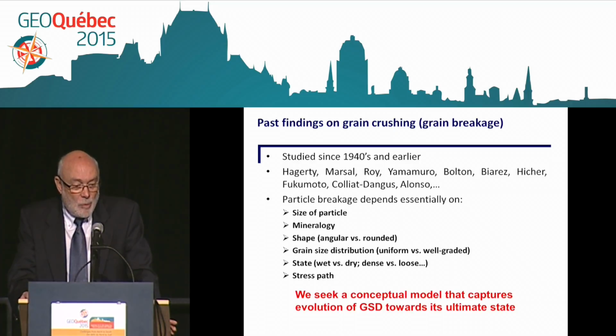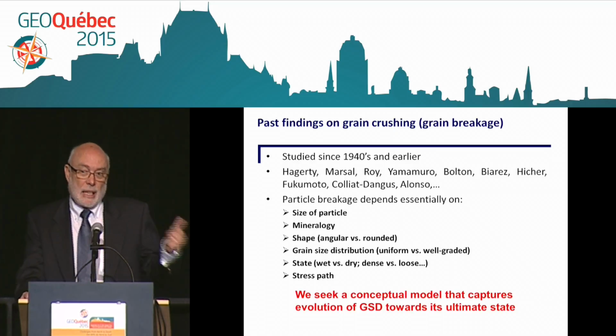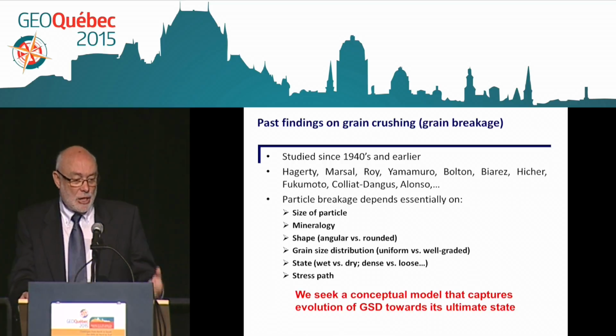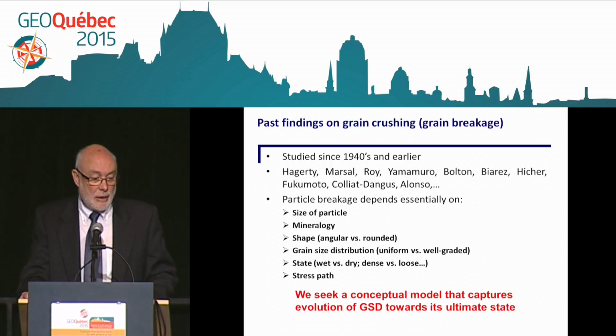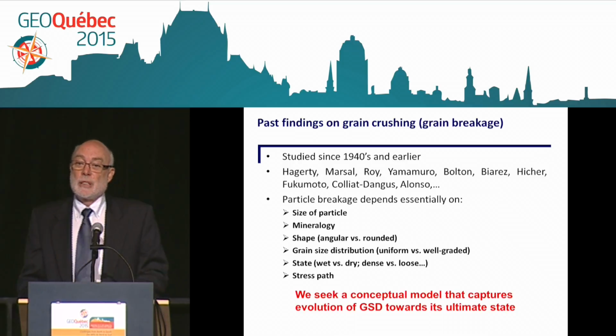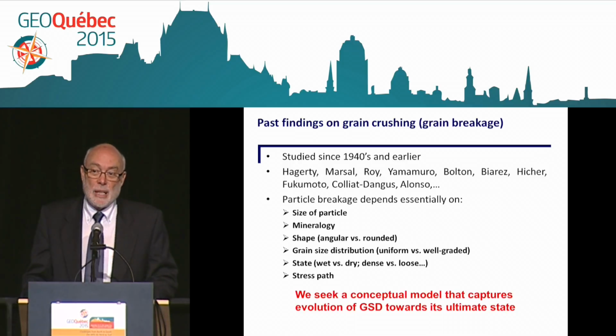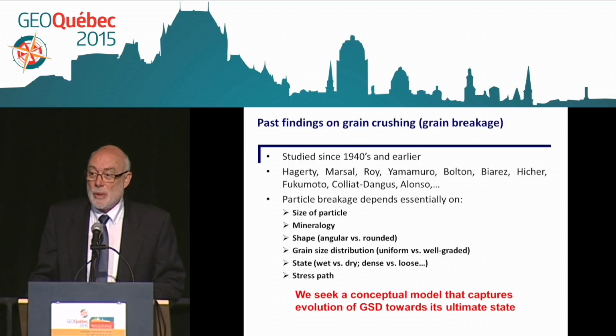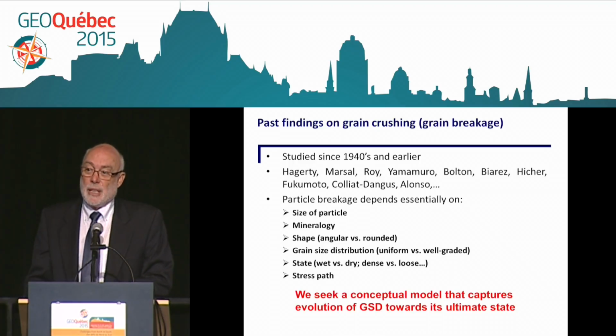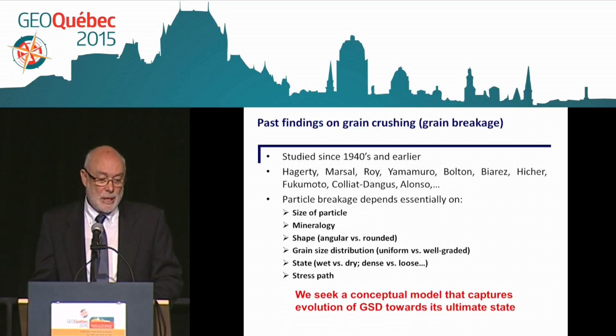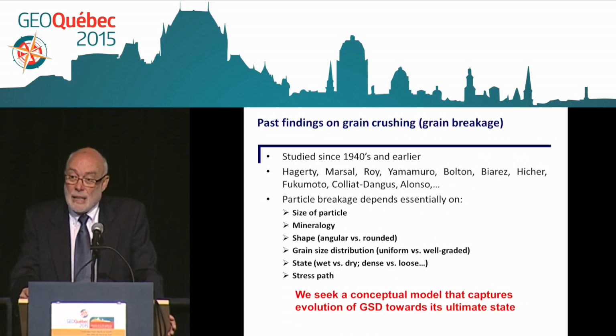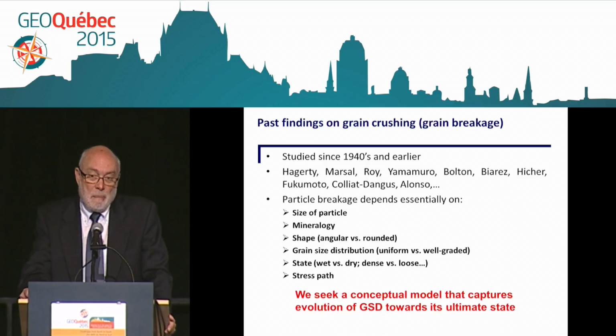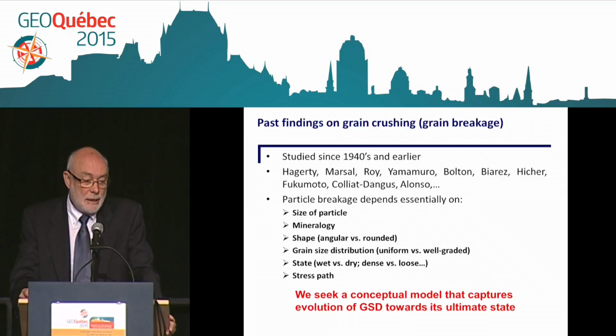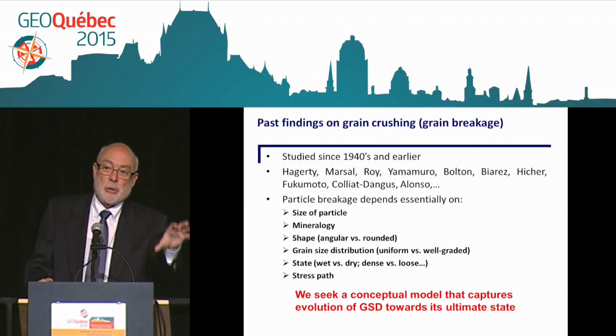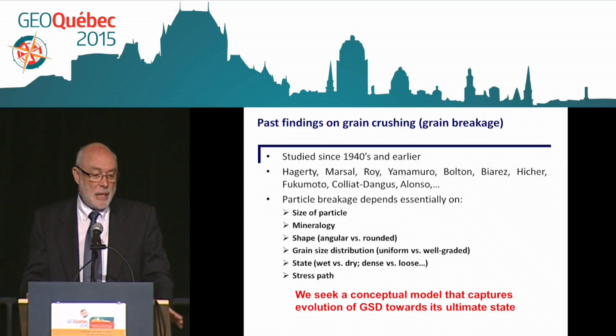So we now know particle breakage depends essentially on size of particle, mineralogy, shape, angular versus rounded, grain size distribution, uniform versus well-graded. Obviously, well-graded material will be more resistant to further grain size changes than uniform material, as you will see in a minute. State is saturated versus the dry state. Saturated will be less resistant. So there will be a difference between upstream shell behavior and downstream shell behavior.